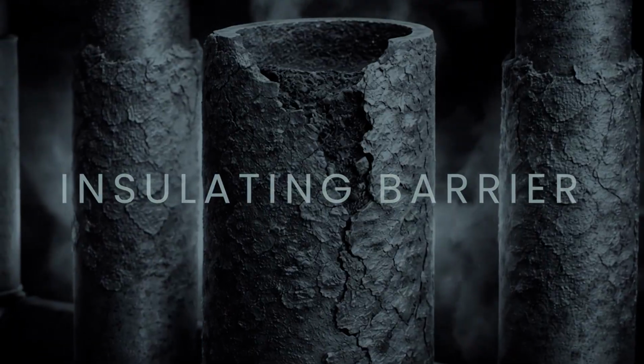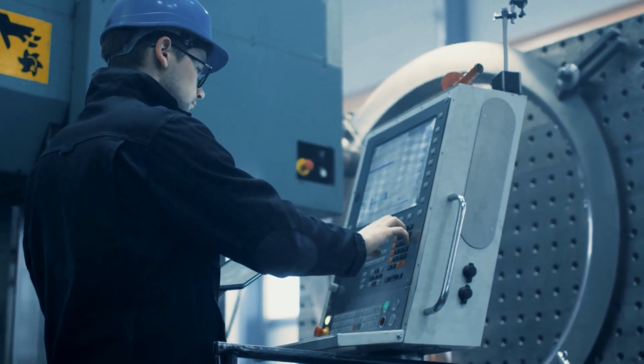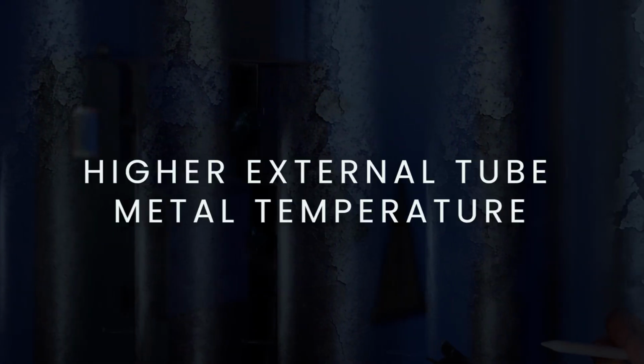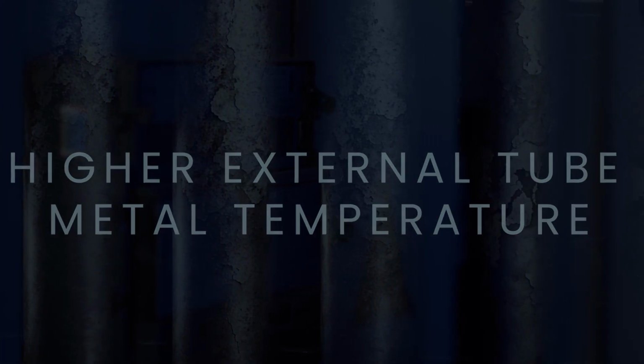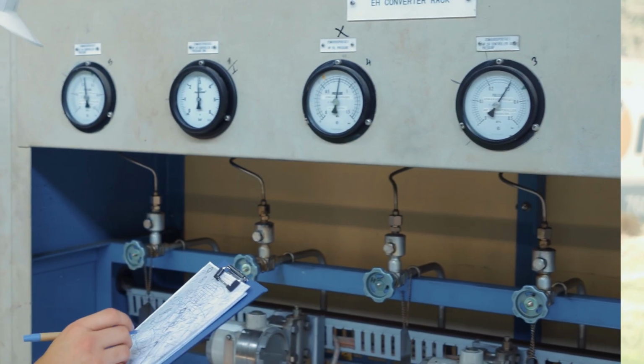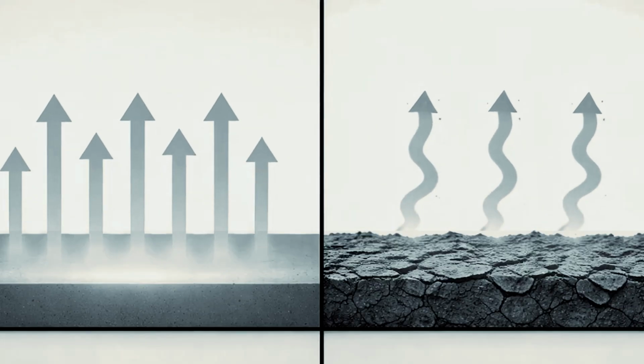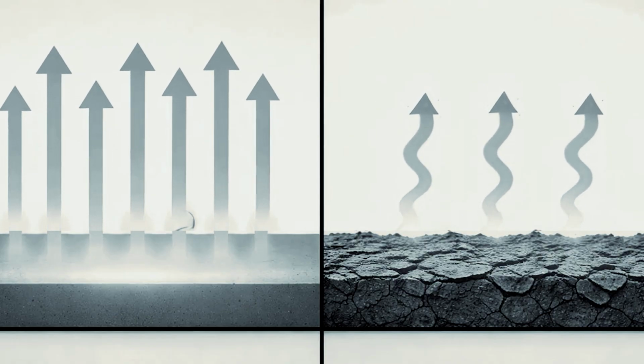Now, as that layer grows, the resistance to heat transfer increases. So, to maintain your normal process temperature and throughput, operators must therefore increase their fire duty, turn up the burners. This drives a higher external tube metal temperature, and now you're pushing yourself to the limits of design on your bridge wall temperature limits. Now, over time, this compounding effect, more heat, more oxidation, more scale, does become quite problematic. And we can eliminate that entire scenario.